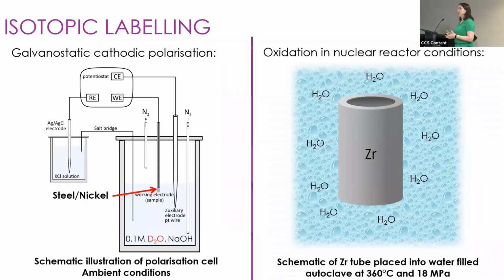For the zirconium alloys, in this case, they're being used as the fuel cladding for the uranium fuel in nuclear reactors. So what we wanted to try and do is to investigate their oxidation behavior and hydrogen pickup in simulated reactor conditions. In a reactor, our zirconium tube is going to be sitting in water at high pressure and high temperature, such as these conditions here. So what we do with the zirconium alloys is we grow the oxide initially to a certain point. Zirconium has a very characteristic oxidation behavior while it goes through a number of transitions of fast growth and slow growth. And so we'll grow it to a particular point so we know whether it's just before one of these transitions or after a transition.